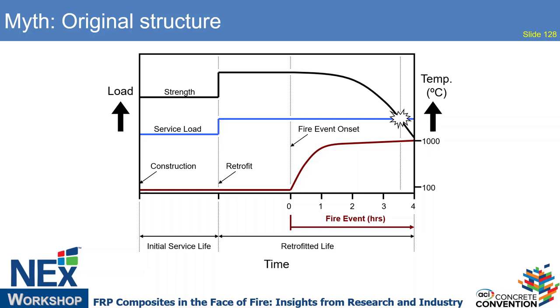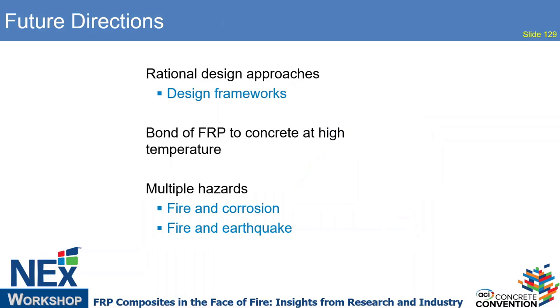This is for, you have service load and you strengthen your structure, then you're increasing basically the expected service load because you've done that strengthening. And then if you have insulation, which is shown in this black curve, then the insulation protects and you have gradual deterioration. So you might have after a fire event, like 4-hour fire endurance. But if you don't do any insulation, and you also strengthen it a little bit higher, you may still meet that the original structure can carry the service loads, but without insulation, you lose the FRP quite rapidly in its strength combination. So it just shows you're not going to get equal performance just by doing that, and it could bring you back into needing more fire protection than that.